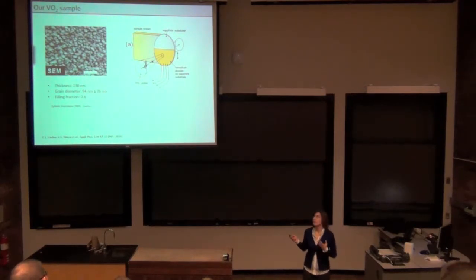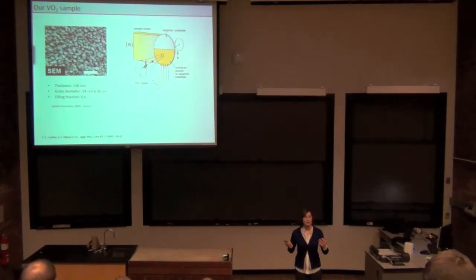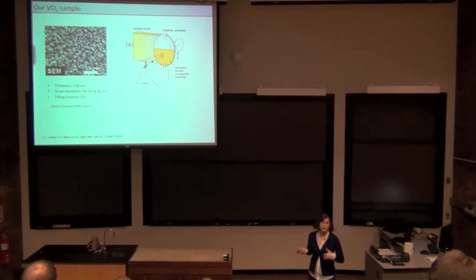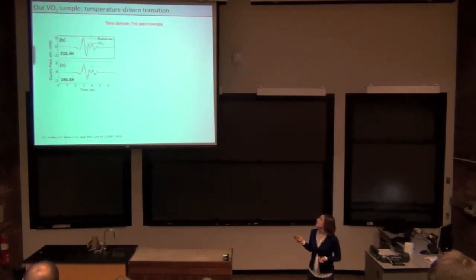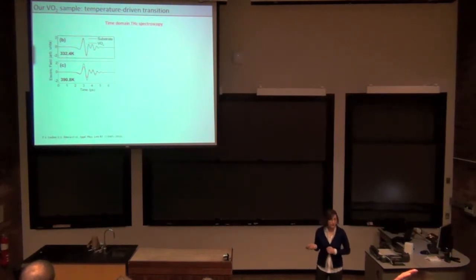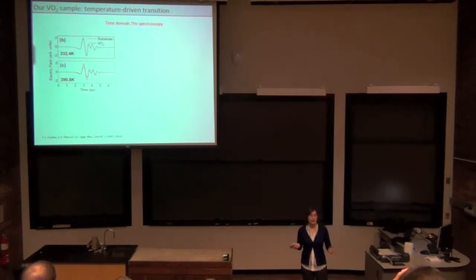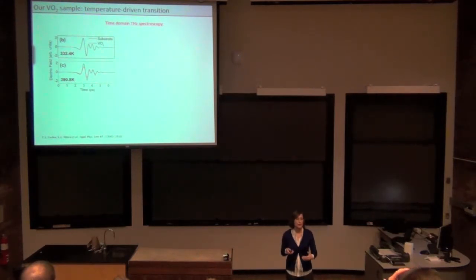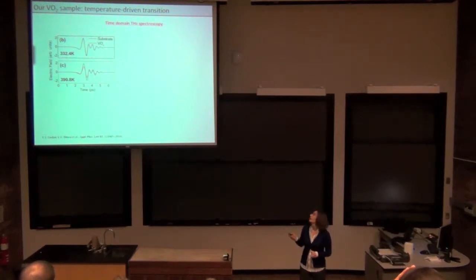So what we did is we studied it at the same time with the normal 4-point probe measuring conductivity, and terahertz spectroscopy without any excitation, just through the thermal transition. So these are the terahertz waveforms transmitted through just the substrate and the sample with the substrate. These are the waveforms below the transition, and this is above the transition. Below the transition, you see there's no difference. The sample doesn't do anything because, of course, it's insulating. There are no free carriers, no other species that can absorb terahertz in this particular bandwidth that we have. Then, as we heat it up, the transmission drops at the peak by almost 34%.